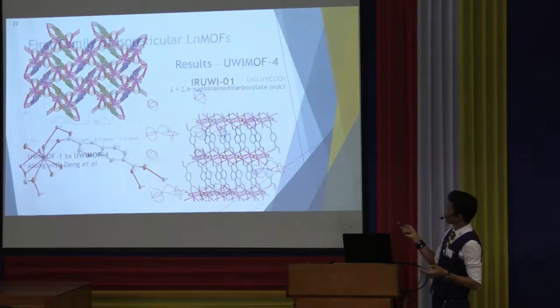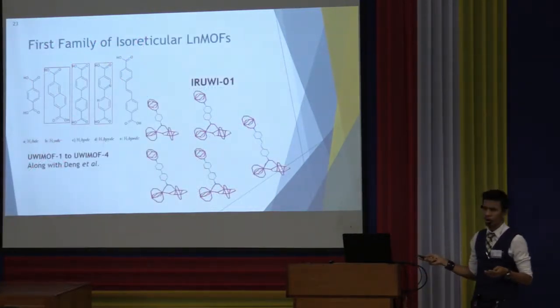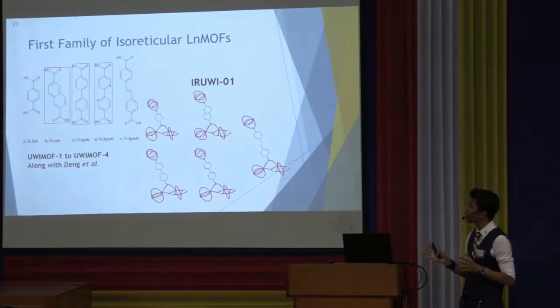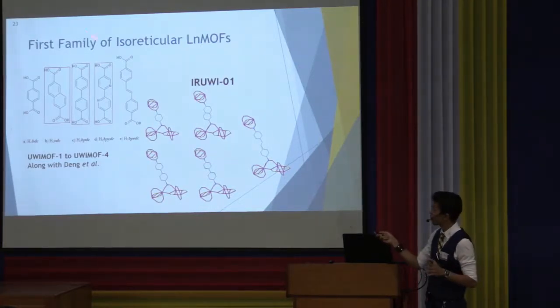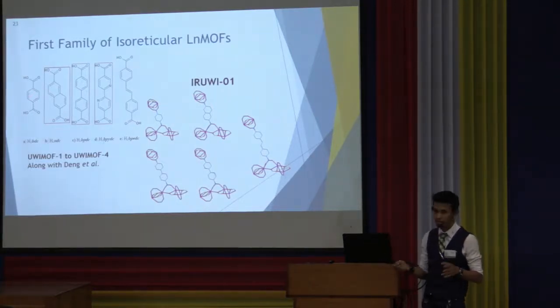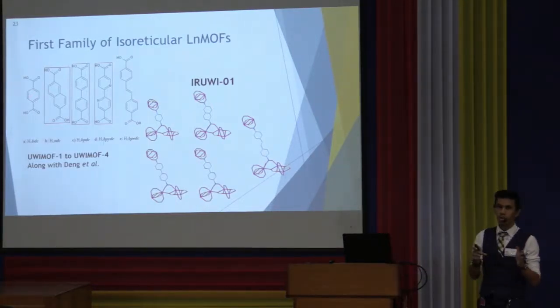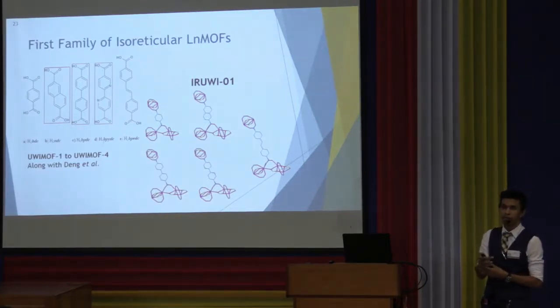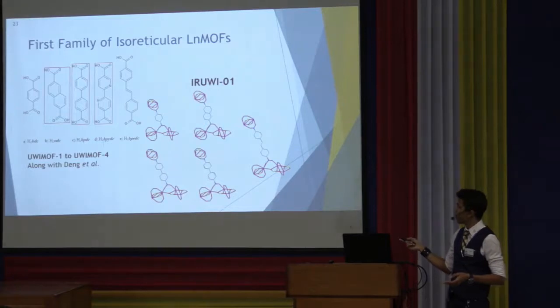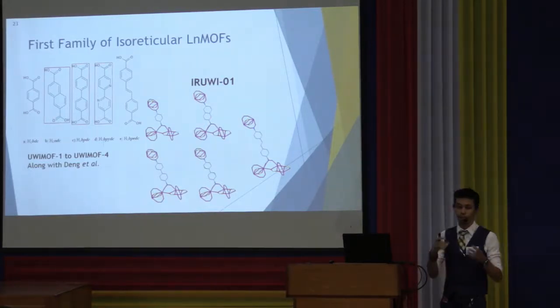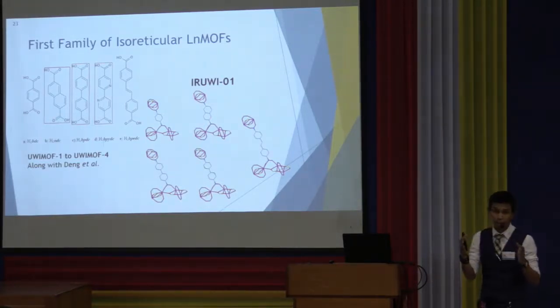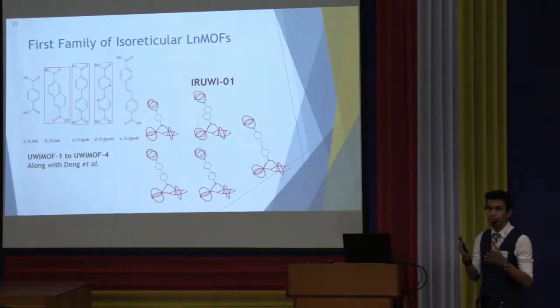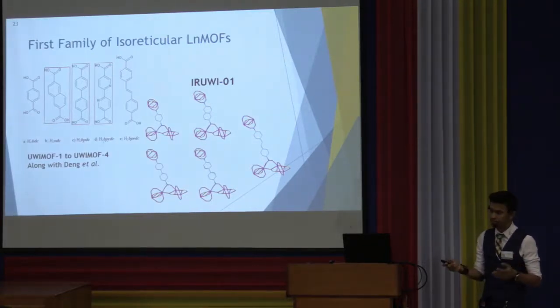So UWI-MOF1 to UWI-MOF4, along with Deng's structure, constituted the first ever family of isoreticular lanthanide metal organic frameworks using these 5 ligands. And not only were they the first ever family of isoreticular LMOFs reported, but MOF 2, 3, and 4 were the first lanthanide metal organic frameworks that were deliberately synthesized by design.